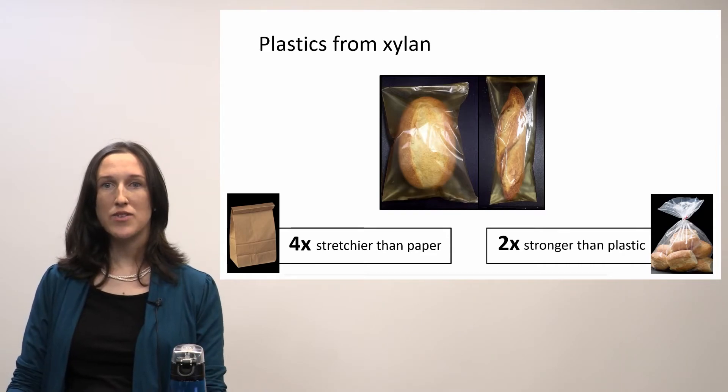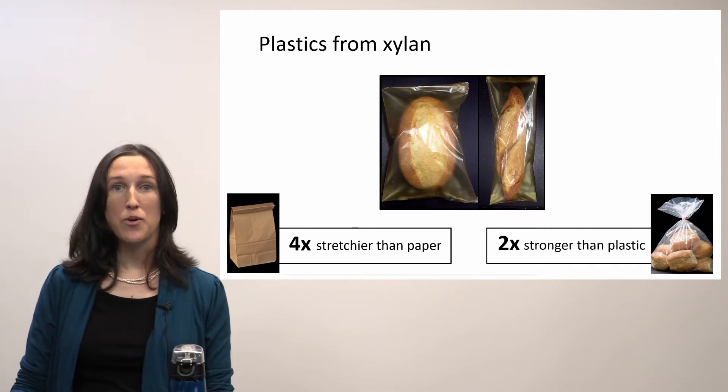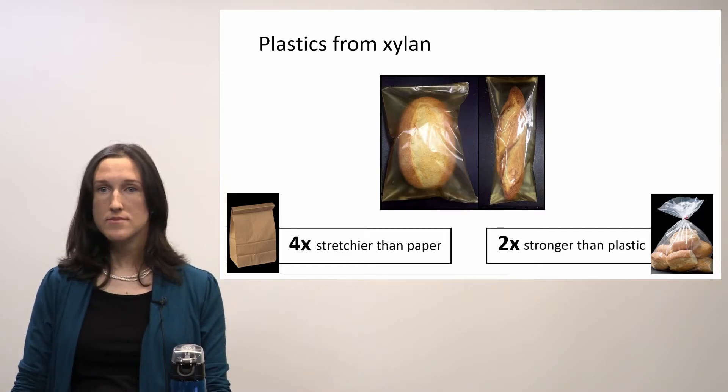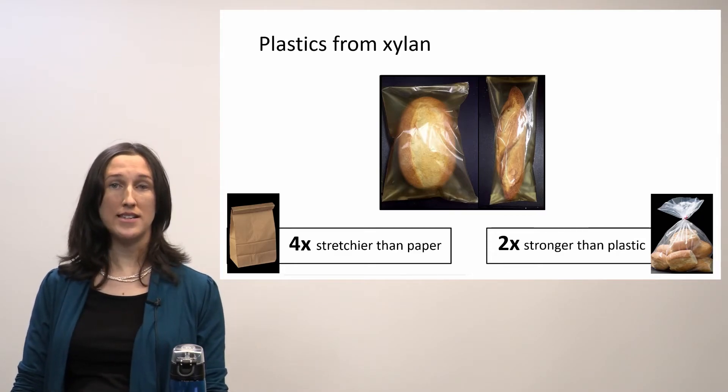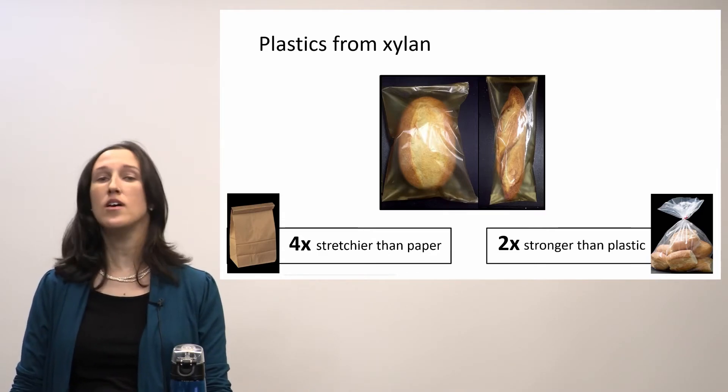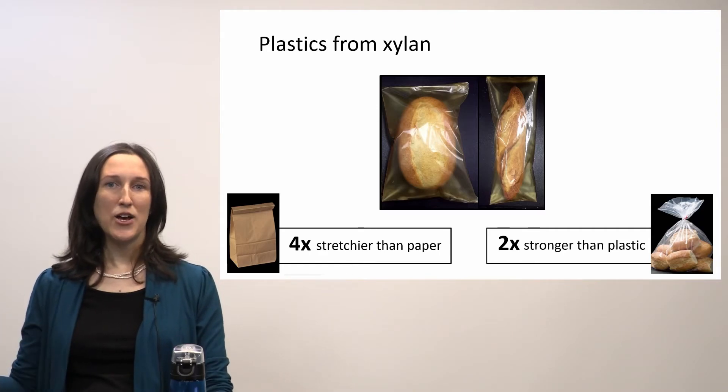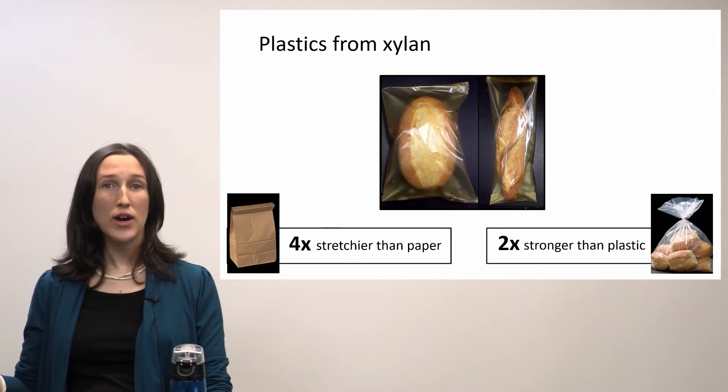So it turns out that this bioplastic is four times as stretchy as a typical brown paper bag. It's also twice as strong as the industry standard for low-density polyethylene. So that was good news.